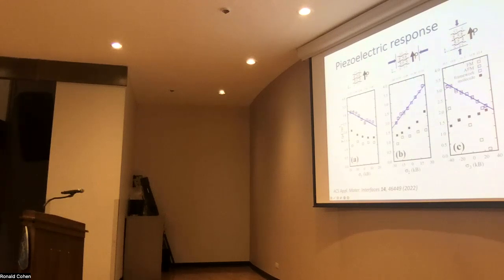On the other hand, if now we apply stress along the A direction, the other transverse direction, here we will observe a response of the opposite sign. What it means is that if we apply tensile stress, we will actually reduce the polarization in the perpendicular direction, and this is something that one would expect. So we realized that this material is actually quite unusual because it can exhibit everything. It can exhibit negative longitudinal piezoelectricity, and it can exhibit both positive and negative transverse piezoelectricity.